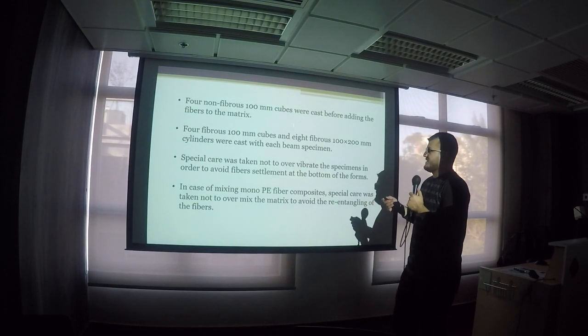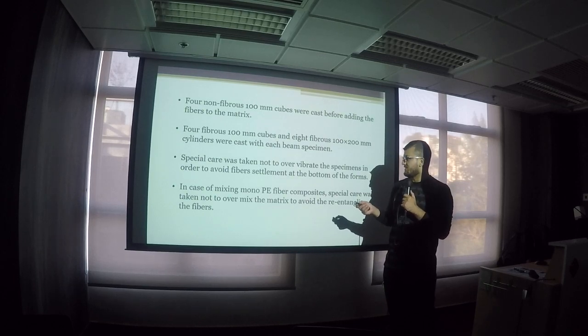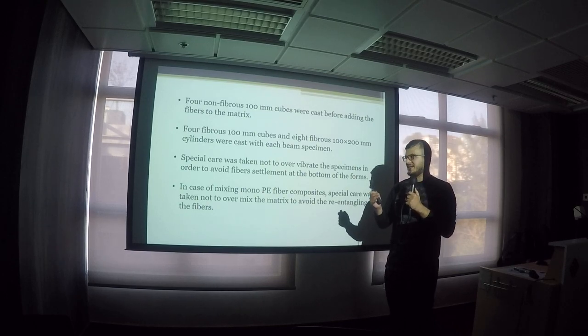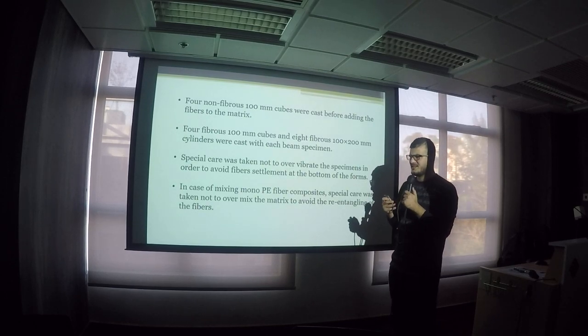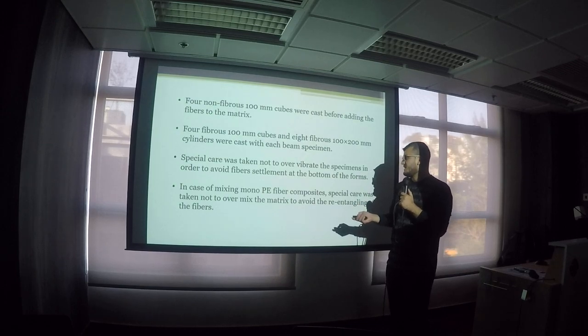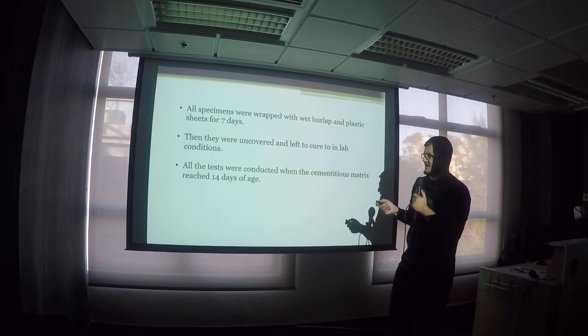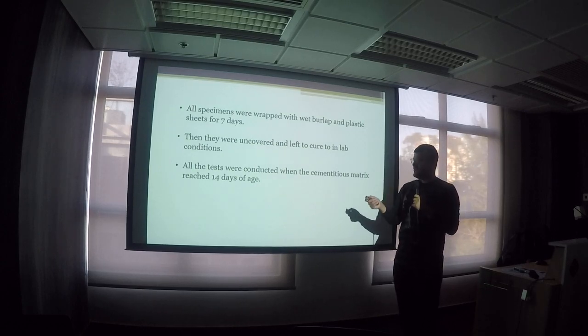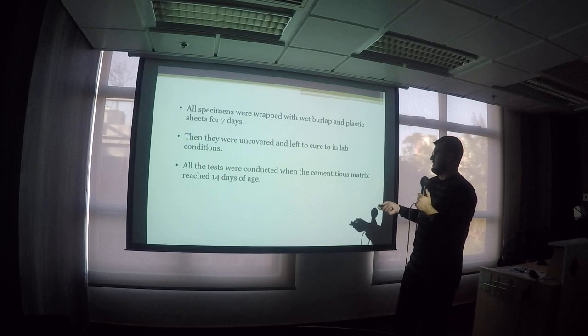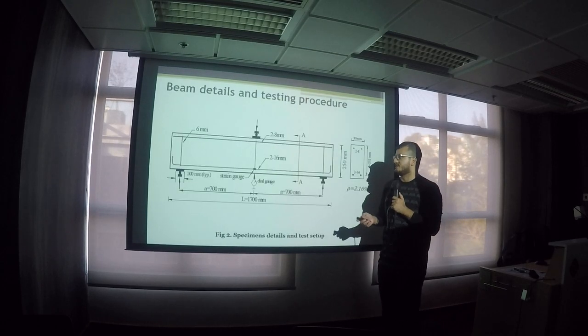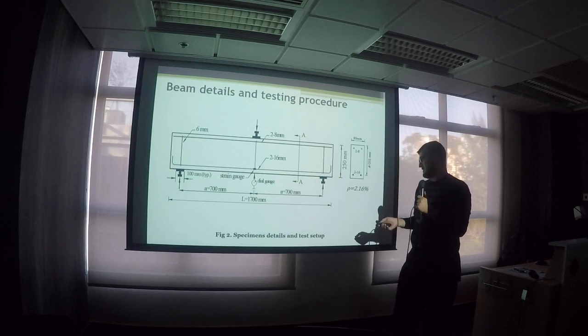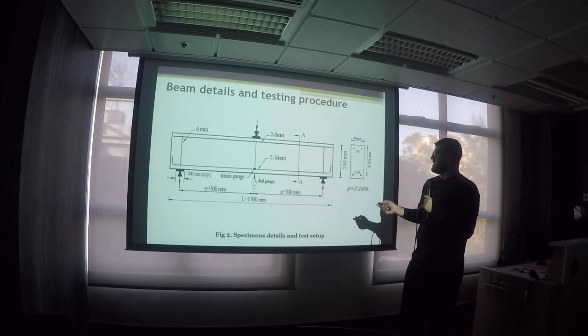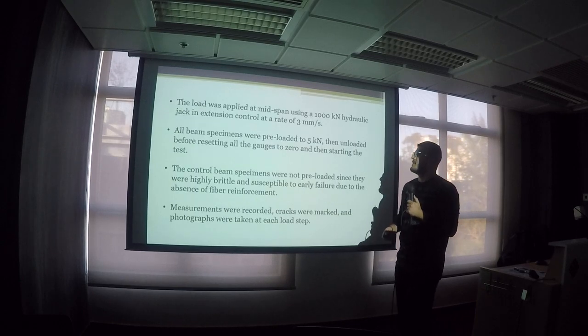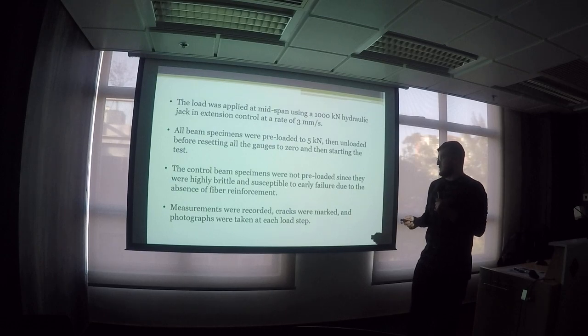Well, we cast some non-fibrous cubes and some fibrous cubes, and as you can see here, we took special care when casting such a material because this is a relatively new material which has not been applied previously on site. All specimens were cured for 7 days, and the test was conducted at the age of 14 days. And this is the schematic figure that shows the beam details and the cross section, and this is the loading condition that we used.